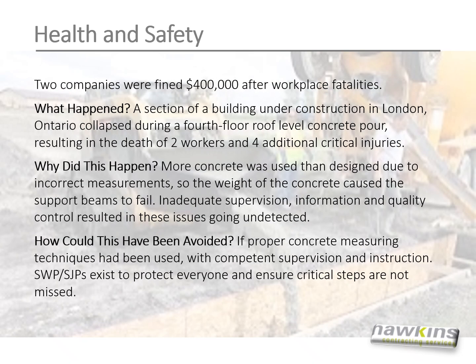Two companies were fined $400,000 after workplace fatalities. What happened? A section of a building under construction in London, Ontario, collapsed during a 4th floor roof level concrete pour, resulting in the death of 2 workers and 4 additional critical injuries. Why did this happen? More concrete was used than designed due to incorrect measurements, so the weight of the concrete caused the support beams to fail. Inadequate supervision, information, and quality control resulted in these issues going undetected.